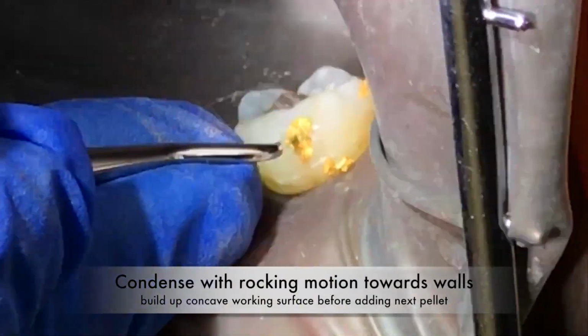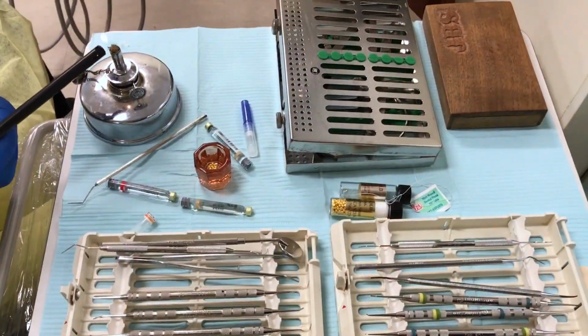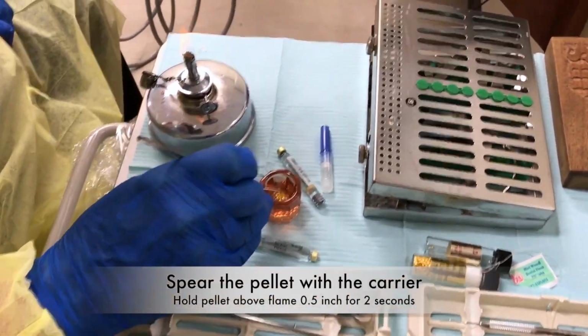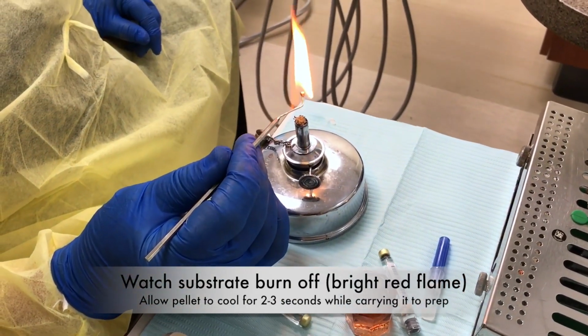Cohesive gold is normally used in the form of a very thin gold sheet or foil, approximately 0.001 millimeter thick. It's called cohesive gold because when the gold layers are laid together and brought into actual contact by pressure, they become permanently united. So on condensation into the prepared cavity, each layer of foil becomes welded to the material already condensed. It is a normal practice to heat the gold foil to about 250 degrees in an electric furnace or a gas flame before use to remove any adsorbed grease or gases that would prevent the efficient welding.